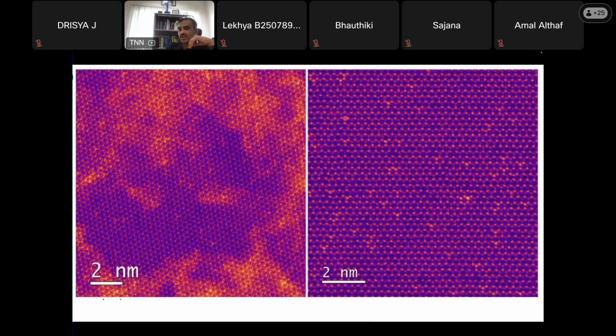And how do I know it is a clean transfer? It's a multi-step process, and even a long exposure to ethanol, which will actually remove all the polymer residues. So after all these steps, on a clean MoS2 surface, you can see there's almost no contrast difference anywhere. It's a uniform contrast, indicating that nice hexagonal crystals are being formed.